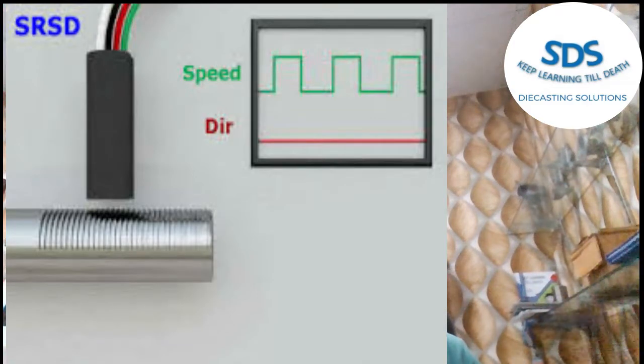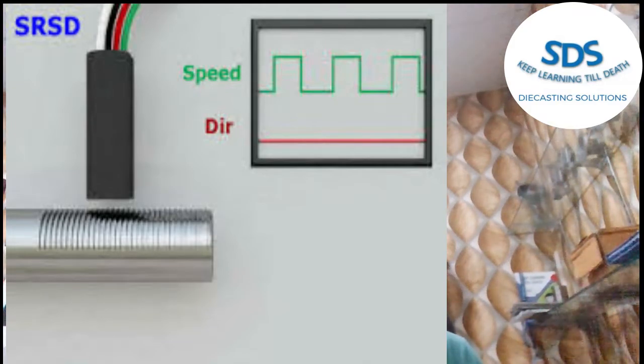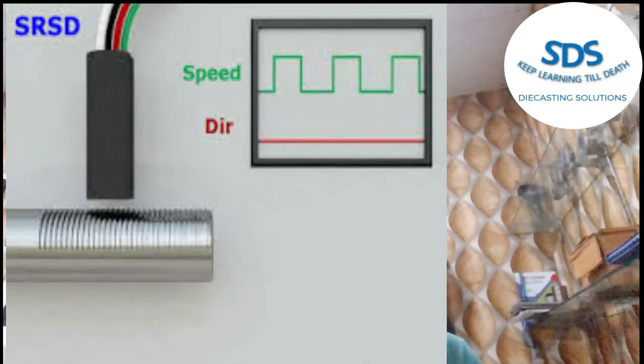For example, a shot valve that controls the first shot phase is open at 59 percent of maximum. This worked well for the last 100 shots, but in the last 10 shots the average shot speed dropped by 2 inches per second due to added friction in the shot, and the process tolerance is plus or minus 1.5 inches per second. The system then adjusts by 1 percent — to 60 percent from 59 percent — on the next shot to increase the shot speed.